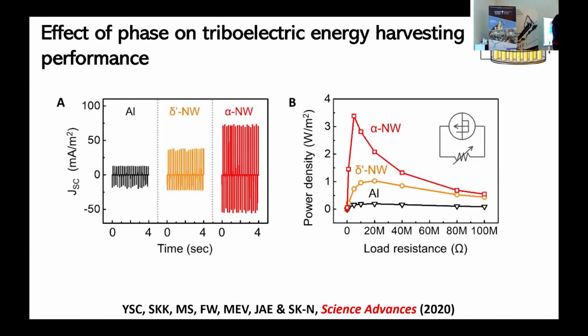Again, the only way to see if this is true is to make a device. So a typical device would have two different parts. You've got your nanowires on one side. We use Teflon, which is very tribonegative, on the other side as a counter material. And you've got electrodes on either side. As you tap or rub, there's some charge transfer that takes place. Charges are induced on the electrodes, and then they flow through an external circuit. So this is kind of what it looks like.